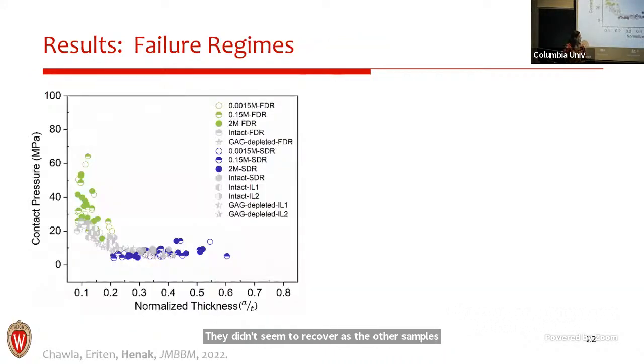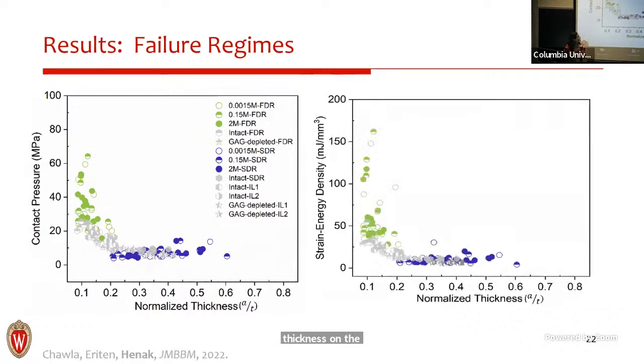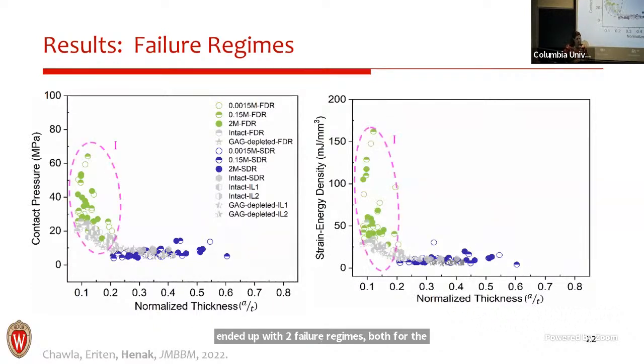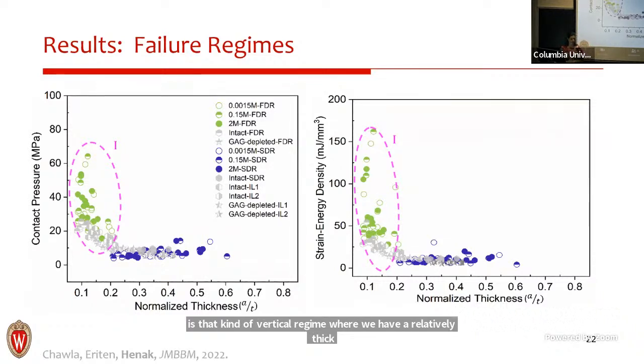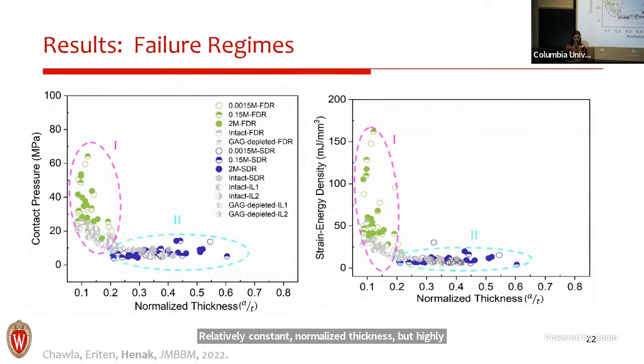When we looked at our 2 failure regimes, we plotted the data from all of the studies together. So the intact and GAG depleted are the gray data. The different osmolarity are the purple and green data. Here we have contact pressure on the vertical versus normalized thickness on the horizontal. And from this data set, we ended up with two failure regimes, both for the contact pressure and for the strain energy density. Regime 1 is that vertical regime where we have a relatively constant normalized thickness, but highly variable contact pressure and strain energy density. Whereas in regime 2, we have a relatively constant contact pressure and strain energy density, but a highly variable normalized thickness.